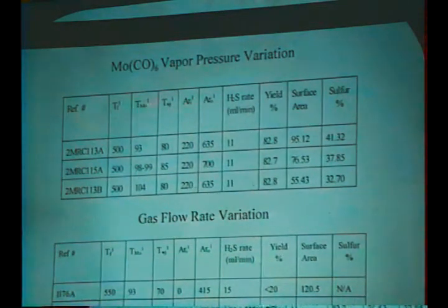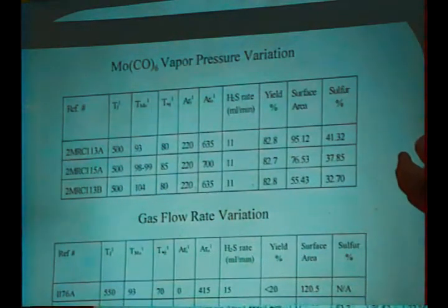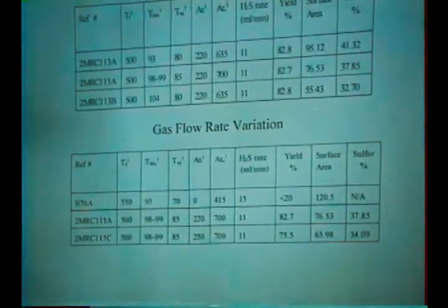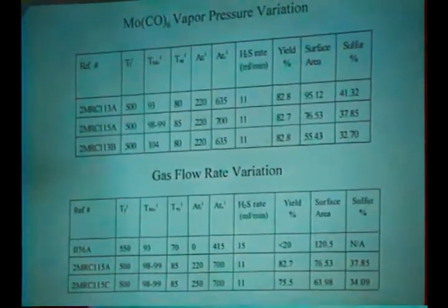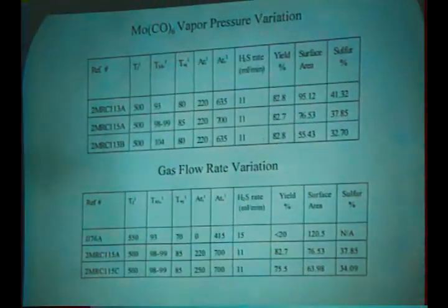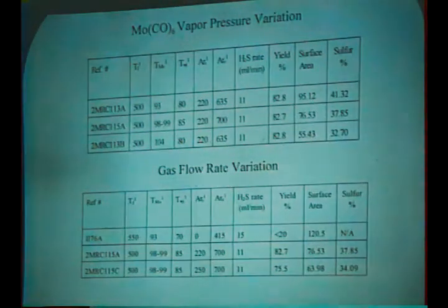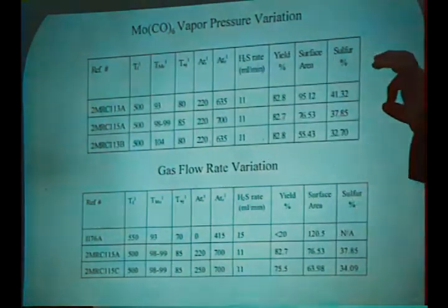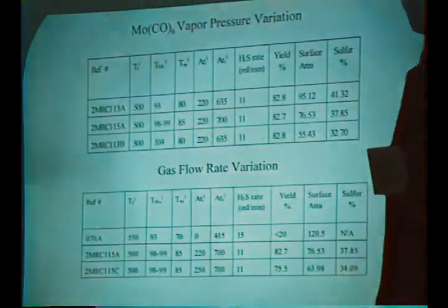And going from a carbonyl temperature of 93 to 104, you'll see a corresponding surface area change from 95 down to 55.43. So what I'm essentially doing is increasing the flux of the reactor, increasing the concentration of the molybdenum carbonyl in the reaction, which then lowers the surface area, which is consistent with any type of co-precipitation reaction. As concentration is increased, typically you get a decrease in surface area. What you'll notice here too is the sulfur concentration decreases with increasing molybdenum temperature. The reason for that is, of course, you're increasing the amount of molybdenum carbonyl present and decreasing the relative ratio of H2S to molybdenum carbonyl, which is shown in the products of the reaction.